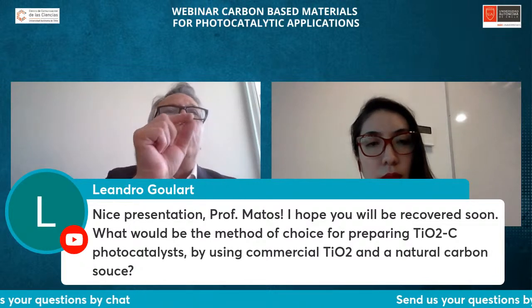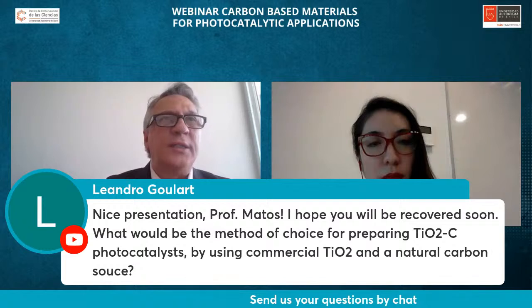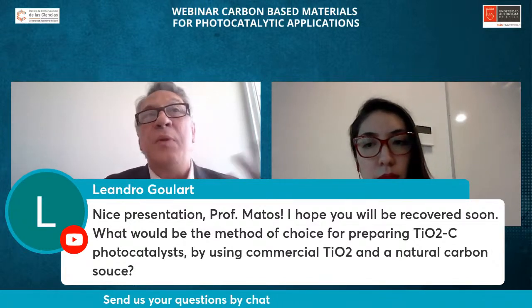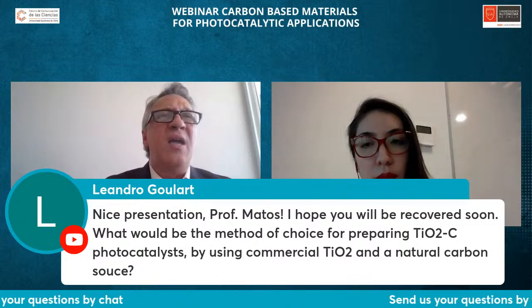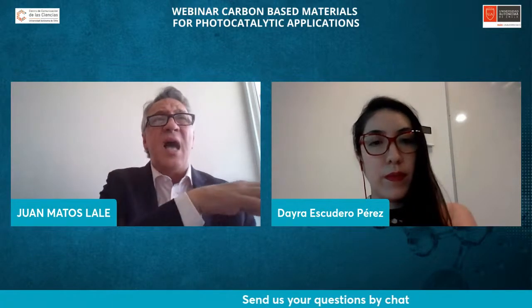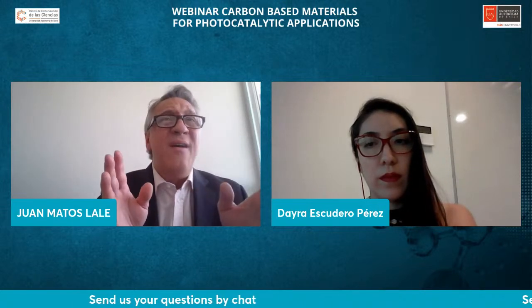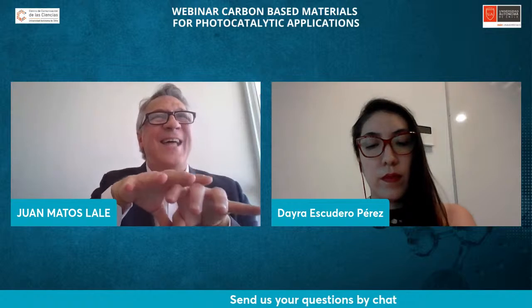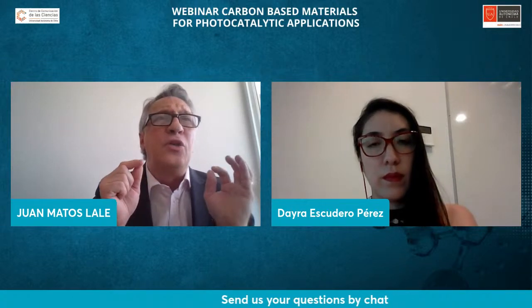It's very tough to control carbon quantum dots if you use another kind of possibility. The reason is because the formation of titanium dioxide is an acid-promoted reaction. It's a hydrolysis. If you are dealing with a starting point, for example, an alkoxide, such as isopropoxide or butoxide, the hydrolysis is very fast. And if you have a very labile proton, the gel is formed so fast that the size of the crystals is too high. So we are dealing most of the time with a very controlled pH of the reaction conditions. That is the trick of my group.